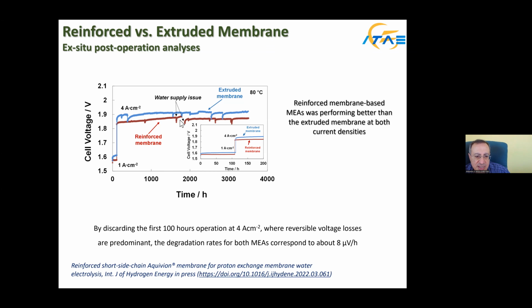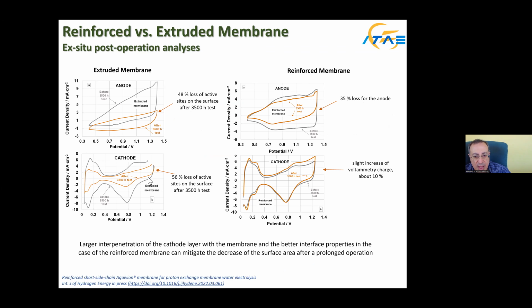In this case, we had a water supply issue, and you can see the efficiency was decreasing immediately, but after solving the problem, we achieved nice efficiency. Also, using reinforced membranes, we have a nice interface with the electrocatalysts.